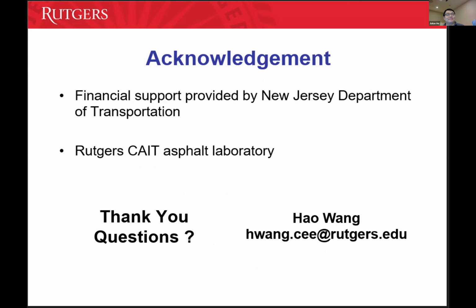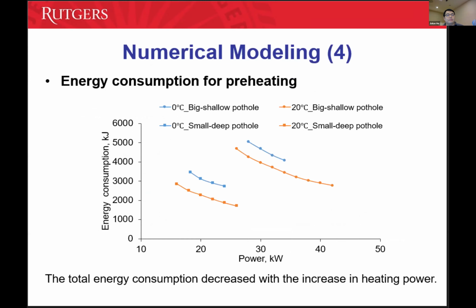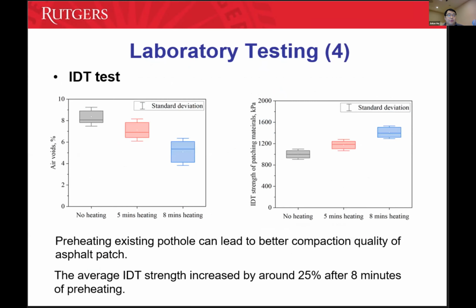Thanks, Hao. Great presentation. One thing we noticed when we did the synthesis, and this question has two parts: maybe the most critical thing is always the density, right? Because you don't want water to infiltrate and create potholes. Did you do any density check to see if the preheating helps? I'm assuming the cohesive strength is probably a function of that density, but did you do any density check to ensure that? I think we happen to have some measurements on the left. Okay, I missed that. Yeah, perfect. So that's exactly what we expected.